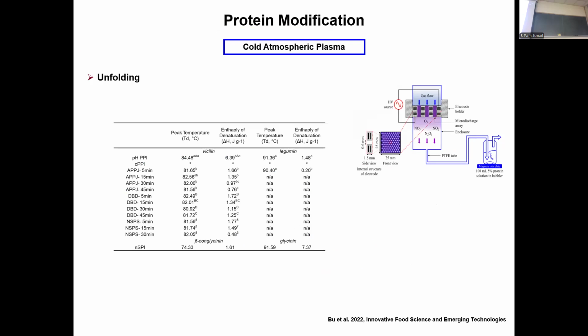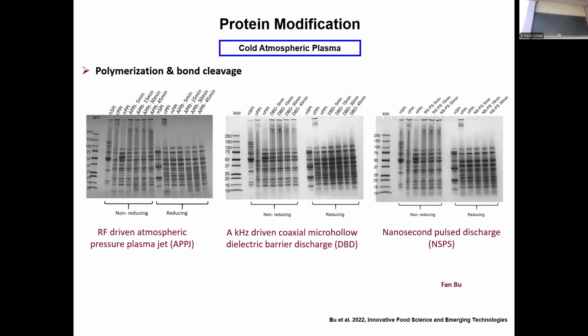We tried different sources of plasma, 3 different types, 3 different temperatures, and 3 different times. We did that with pea protein, and we looked at the unfolding through the enthalpy of denaturation. Every treatment resulted in unfolding of the protein, with, of course, the more exposure, the more the unfolding. The 3 different cold plasma geometries we used are the plasma jet, which George has in his lab, but we did that at mechanical engineering. They built for us a unit for dielectric barrier discharge, and another unit for nanosecond pulse discharge. They are very different geometries, but in all of them we used argon and air, or argon and oxygen.